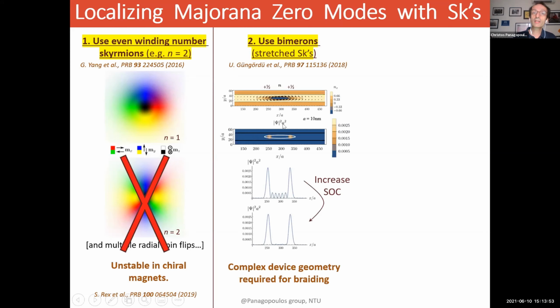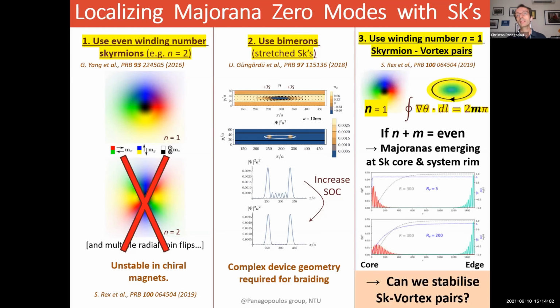The problem with using a bimeron for localizing Majorana zero modes is that it requires a complex device geometry in order to braid. The other possibility is to use a winding number n equals 1 and have skyrmion-vortex pairs. So here, if n plus m, where m is the winding number of the vortex, and n equals 1, then if the sum is even, that would give you Majoranas that would emerge at the skyrmion core and at the system rim.